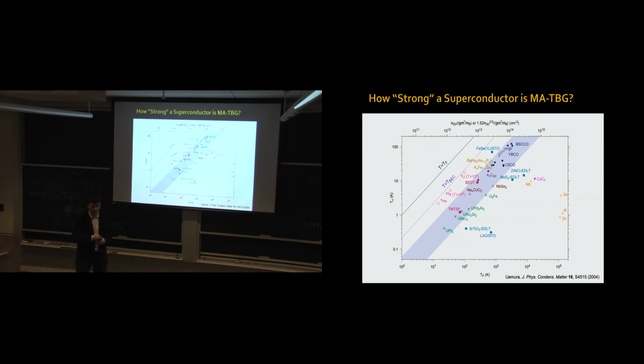As you go from this corner in this direction, you typically go towards more exotic and unconventional types of superconductors. In this blue band here is where most of the unconventional superconductors exist. So you have, for example, high temperature cuprate superconductors here, you have the iron pnictides, the organics, the heavy fermions. I put even data here for ultra cold atoms, lithium-6, potassium-40, both axes multiplied by 100 million so that they appear here. But in terms of coupling, they're the strongest coupled systems that we have, these ultra cold atoms, because the strength of the coupling is tunable here.